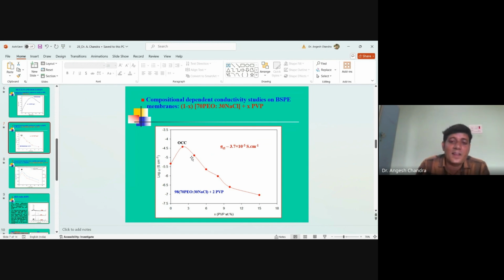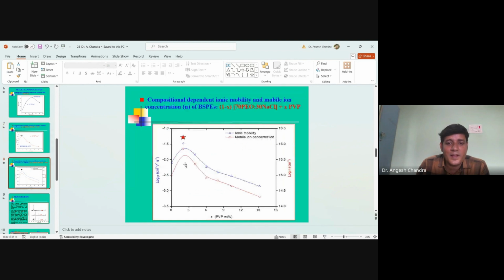The decrease in conductivity is due to the blocking effect created by the polyvinyl pyrrolidone in this blended solid polymer electrolyte system. Now this figure shows why the conductivity increases. What is the reason behind the conductivity increase? We can see here, this shows the ionic mobility and mobile ion concentration plot. As the concentration increases, ionic mobility and mobile ion concentration both increase, and the maxima is found at the same weight percent. It means the overall increase in conductivity is due to the increase in both ionic mobility and mobile ion concentration. These two factors are responsible for the conductivity enhancement in the present blended solid polymer electrolyte systems.